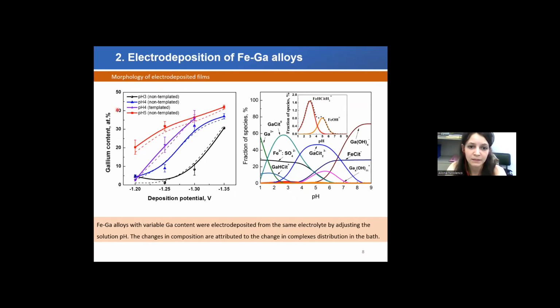So this graph here on the left-hand side shows you the change in alloy composition as a function of electrodeposition parameters such as deposition potential and the pH of solution. We can observe that at a given potential, there is more gallium incorporated in the film when the pH is increased. To understand this behavior a little bit, we performed some species distribution calculation that is shown here on the right side. And indeed, we can observe that when the pH is increasing, there is an increased concentration of gallium hydroxide species, like this one here and this one here. And we know from literature that these species are quite electrochemically active, and they participate in the electroreduction mechanism.